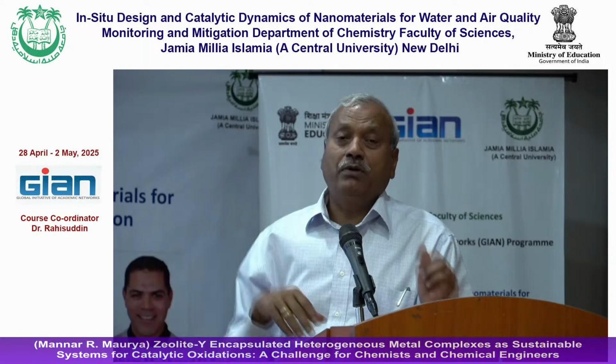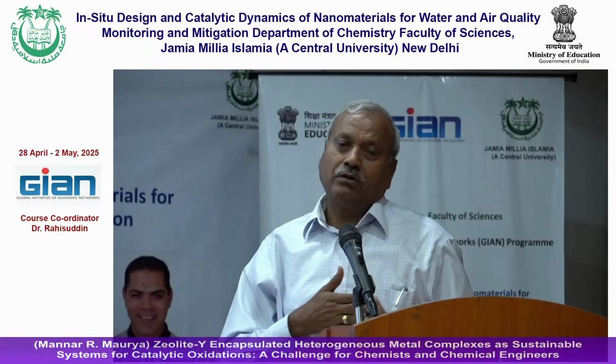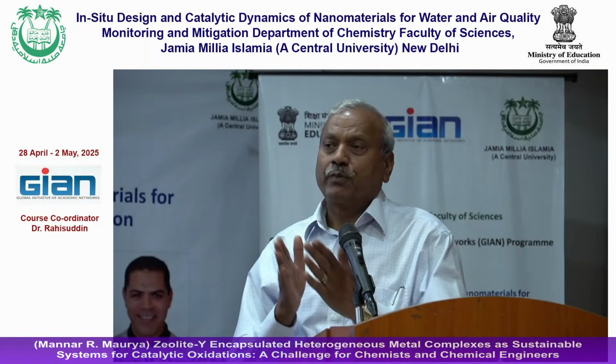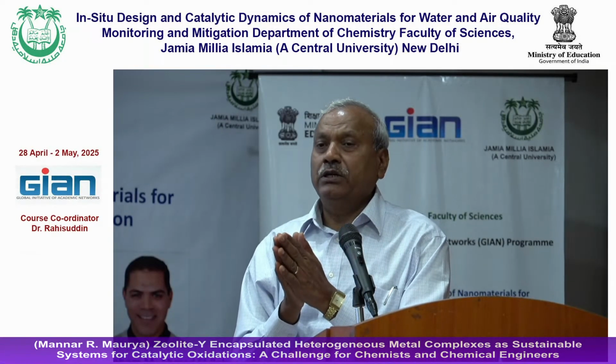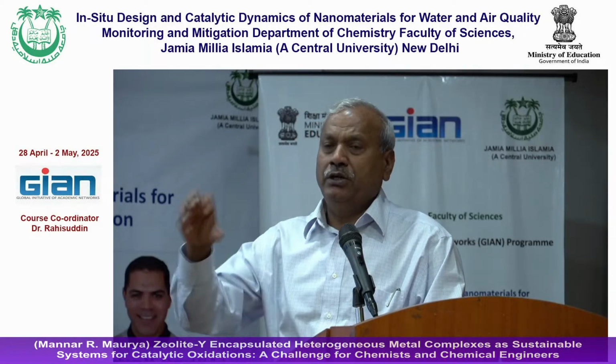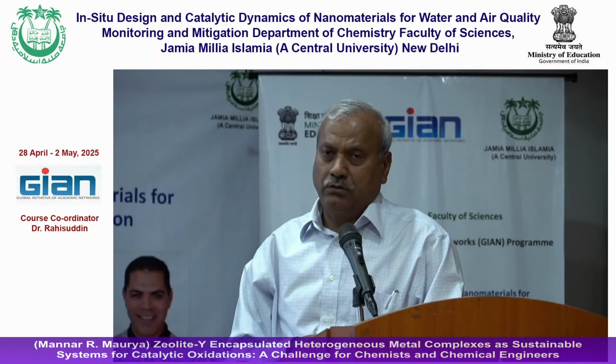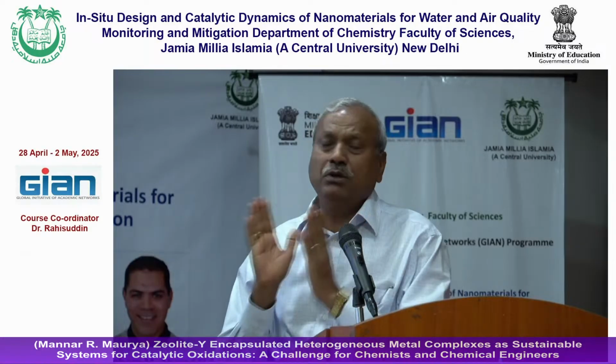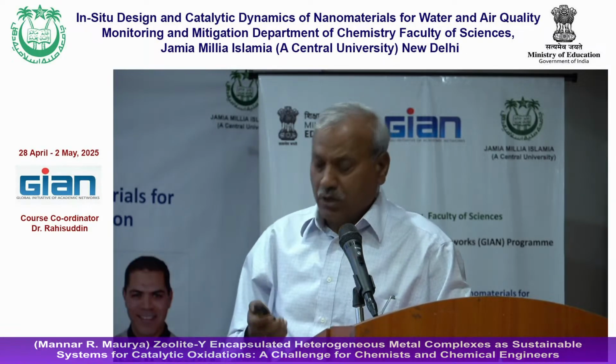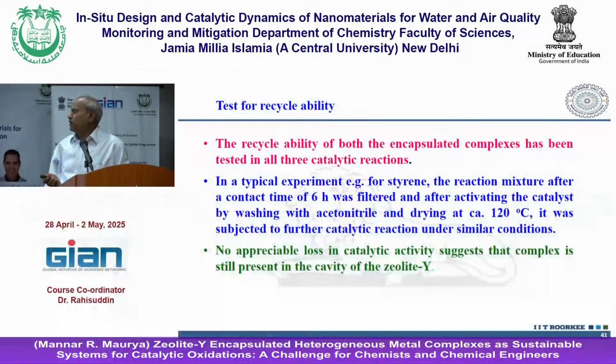Another way, we have also done this. Separate the product from the reaction mixture, wash the zeolite-encapsulated complex with acetonitrile, dry at 120 degrees, and do the further reaction. Taking the same amount gives almost the same product, the same conversion. It means the catalyst is very stable and not reacting. Okay, so we have moved further.